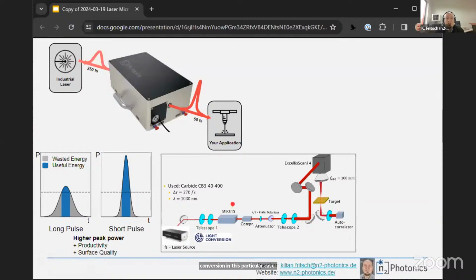We used a beam expansion telescope to adjust the laser to our module. It's called MKS15, a German abbreviation for multipass impulse compressor Stufe. It's a single stage system. We compress the pulses down to 67 femtoseconds. We have a broadband polarizer and thin film polarizer to form an attenuator. Guide the whole beam through another telescope to make it larger for smaller spot size, to a scanner head and an f-theta lens onto our target.